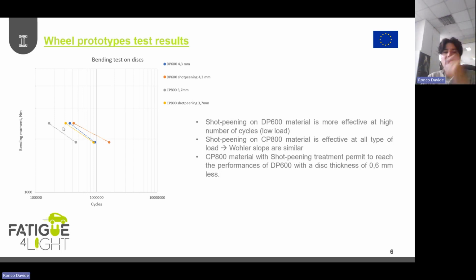Then we made the mechanical treatment, so the shot peening, and as is visible, the DP600 shot peened, that is the orange one, improves the performance, but only, we can say, at a high number of cycles, so low load, changing the Euler slope. While the CP800 improves at high load and low load, and reaches more or less the same performance as the DP600 for 4.3. This permits us to reach the goal because we have a solution that is 0.6 millimeter less thickness, reducing the disk weight by 15%, and so we have a lighter solution.